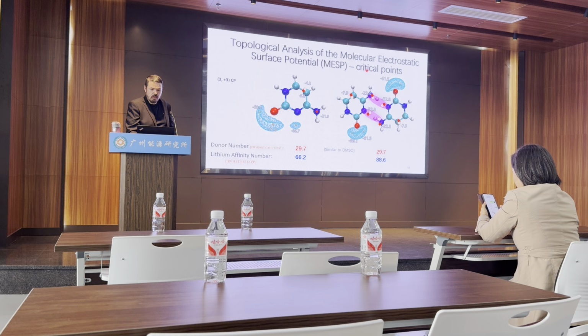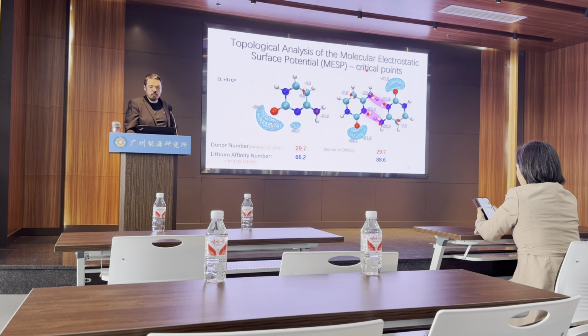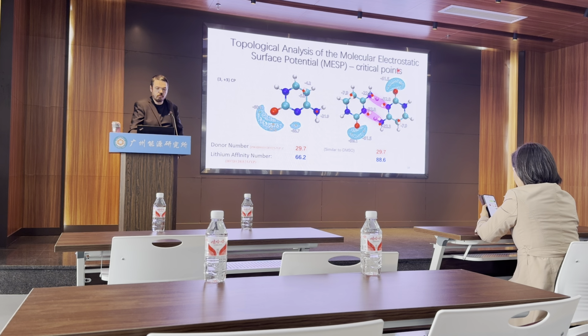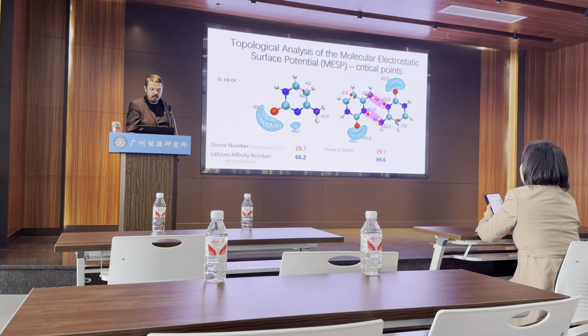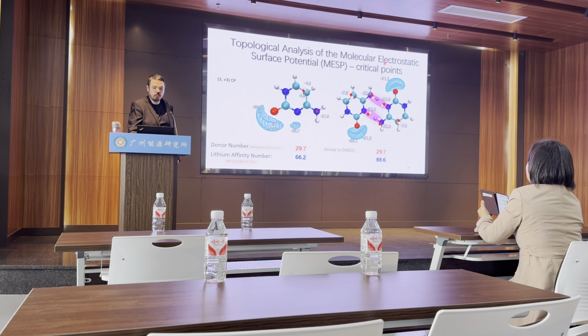So for cytosine, we use this topological analysis of the molecular electrostatic surface potential, so the critical points. The critical points are where we have the most negative charge. So you can see for the monomer, it's just here, a little bit on top. And for the dimer, we can see that it's much more homogeneous, so it's all over. So what we think is that it actually starts blocking the binding moiety when it dimerizes. You can also see the lithium affinity number goes up, so the basicity goes up.